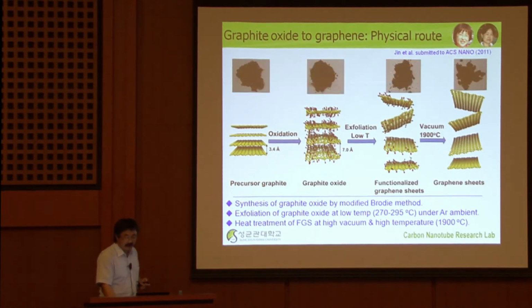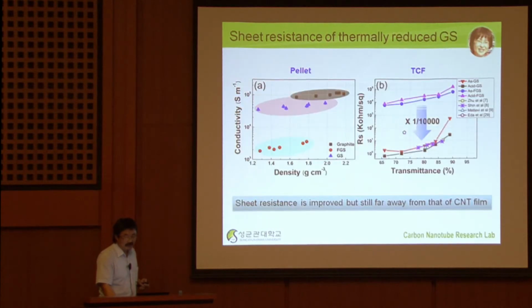So this is actually what we developed in the lab. Again, even using this approach, in the case of pellet formation, the conductivity is very similar to the existing graphite, which is very good. But again, if you make the film, we still have problems, not even close to the CNT. So from my point of view, unless you do something very different, there's no way using graphite oxide to get these highly conductive films, which meets this technological criteria.